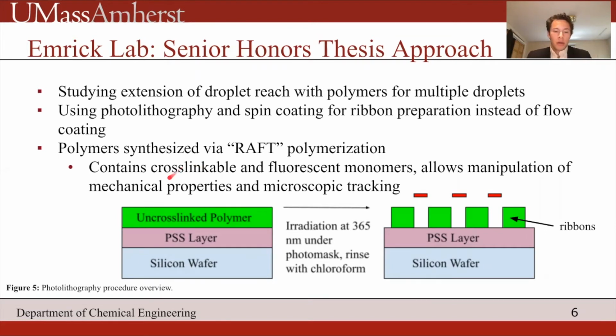And so, for an example of what I'm talking about, we start by depositing or spin coating polystyrene sulfonate, or PSS, onto a silicon wafer. And the premise of this is that PSS is easily miscible in water, and therefore, by placing this in water, we can release the ribbons into solution. And then the uncross-linked polymer is spin-coated on top of the PSS layer.